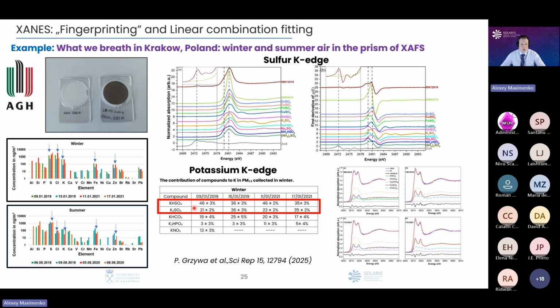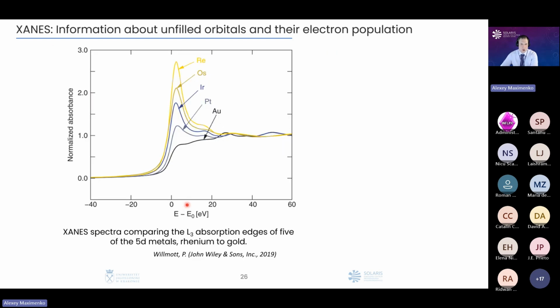proved that in the winter air we have not only sulfates, which can come from the flowers, can come from some kind of standard contamination, but we also have bisulfates, which is a result of burning of solid fuel, which actually should not appear in Krakow because we have a green policy. And that's how this analysis helps us to make the air cleaner in Krakow, because we understand what is the source of such kind of pollution.